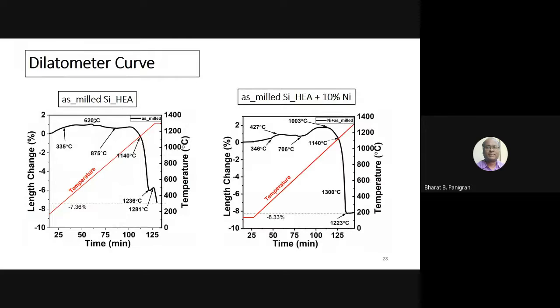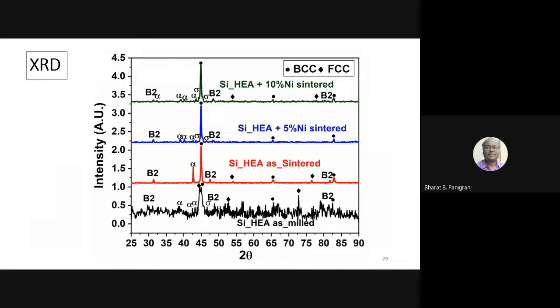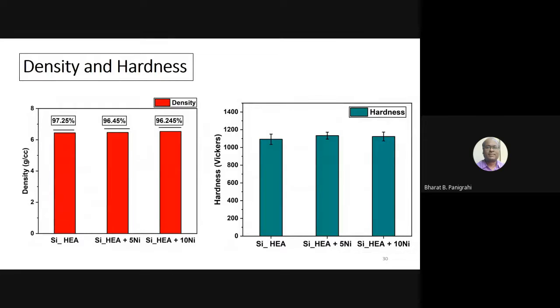These are their typical profiles, so you need not worry about them. The most important part I want to show is when you talk about the density of the alloy. We have a pure high entropy alloy, silicon high entropy alloy. We have added 5% of nickel, and in one case 10% of nickel powder. And we compacted and sintered. Their sinter density is more or less in the same range of 96 to 97%.